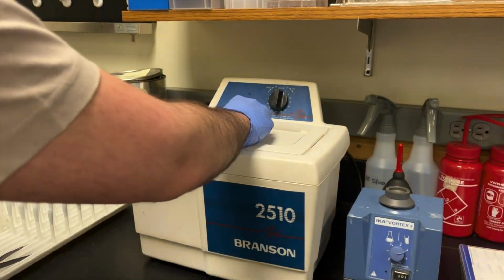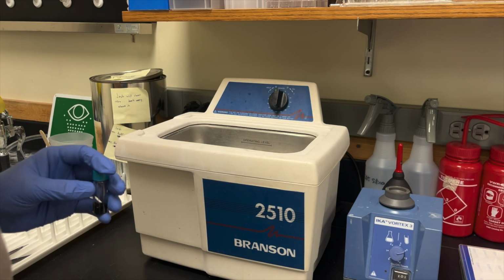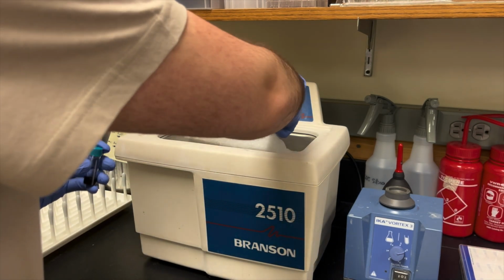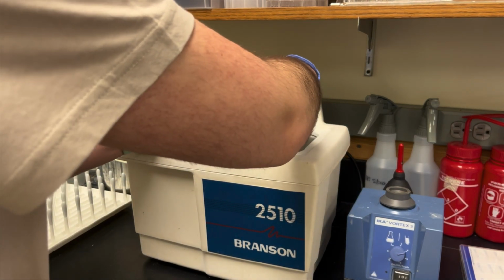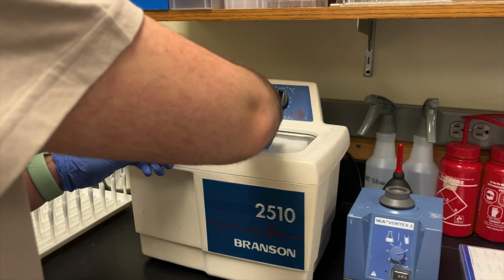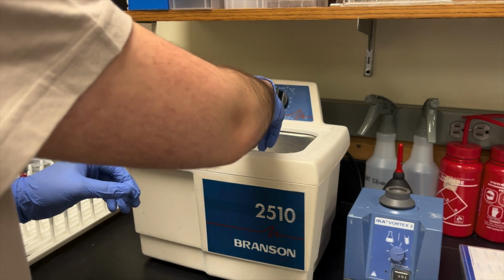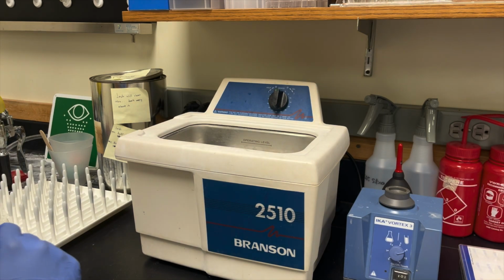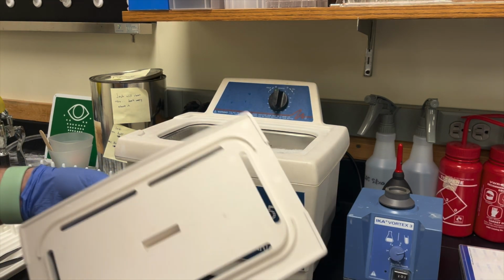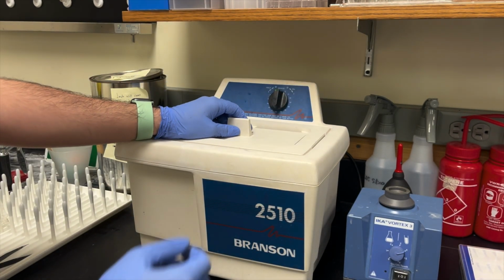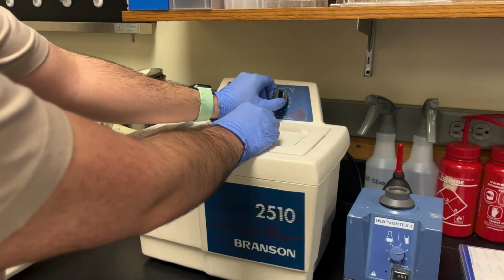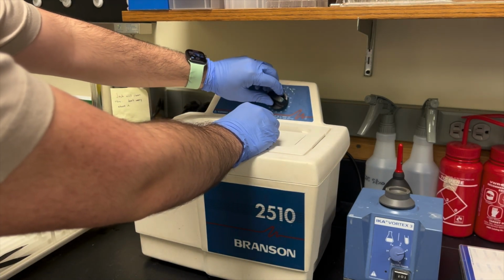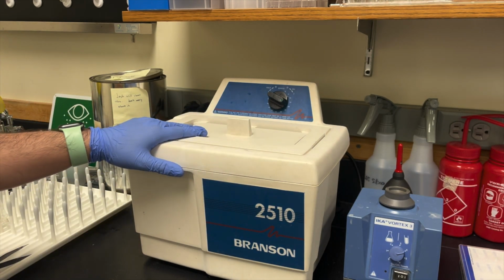After allowing it to stir for 10 minutes, we will transfer the vial into a sonicator. This device helps to mix solutions by using sound waves propagated through water in the container to cause physical vibrations and disruptions in our slurry. This speeds up the dissolution of powders into the binder solution. We will do this 3 times at 20 minutes for a total of 1 hour of sonication.